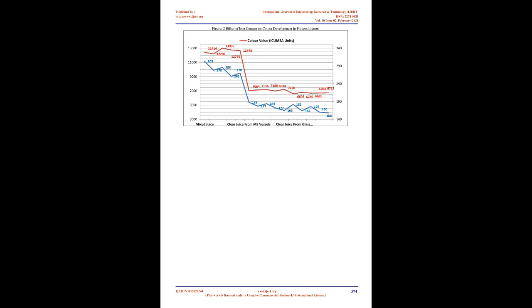Conclusion. On the basis of studies carried out, it may be inferred that the mild steel process equipments in the sugar industry suffer moderate to severe corrosion depending upon the characteristics of process liquors. In general, low pH, below 5.0, temperature above 70°C, higher dissolved oxygen, above 5.0 mg/liter, and lower dissolved solid content, below 40 Brix, of process liquors enhance corrosion rates.